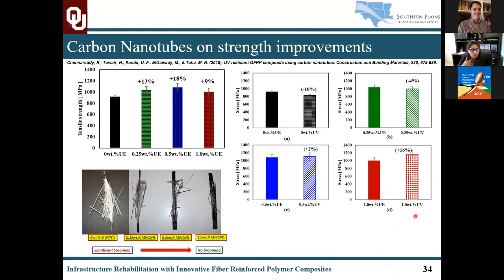For example, 1% weight percent of the resin of carbon nanotubes in a UV exposed sample already shows a 16% improvement in the strength of the material. Of course, the brooming brittle failure can be seen transitioning into a more non-brooming and less explosive failure.